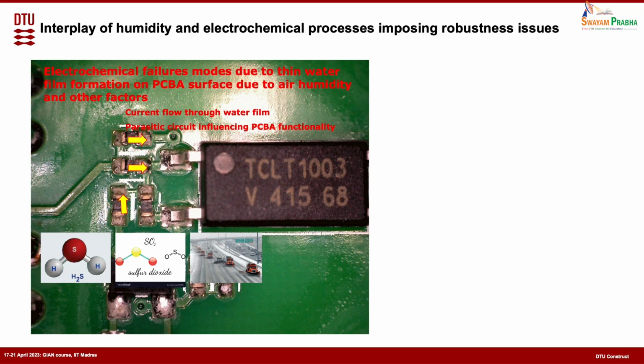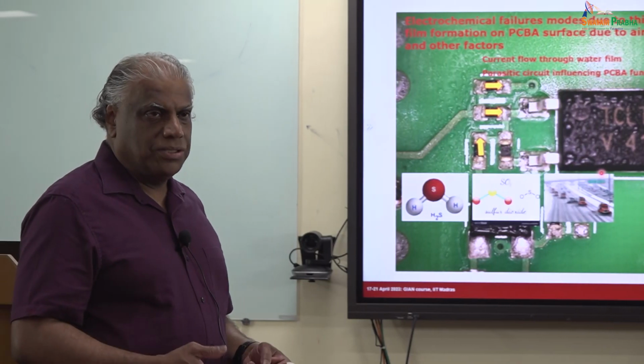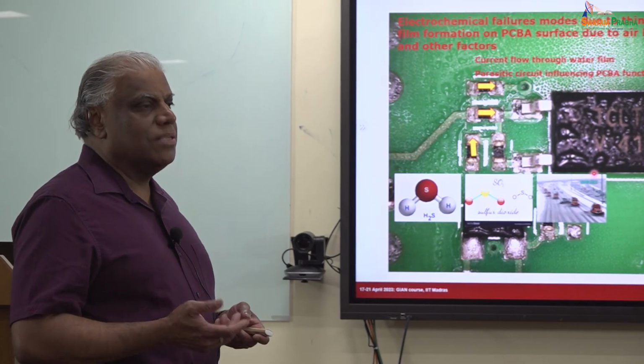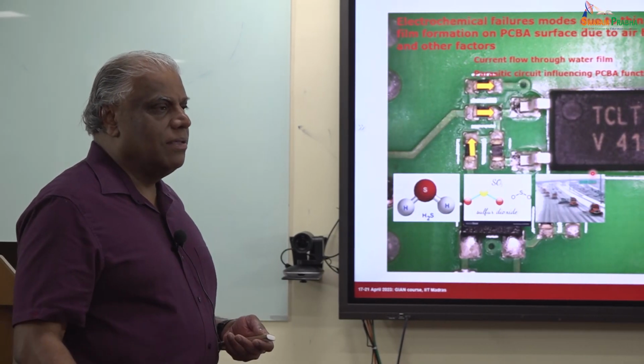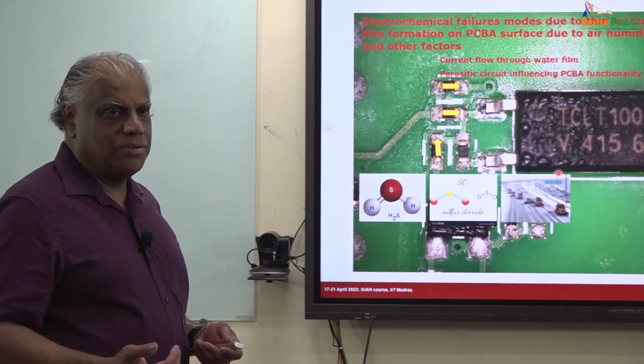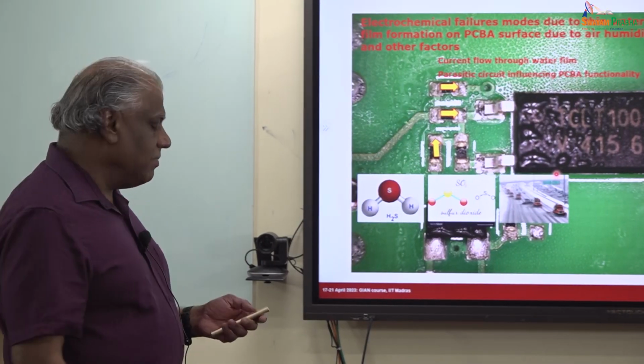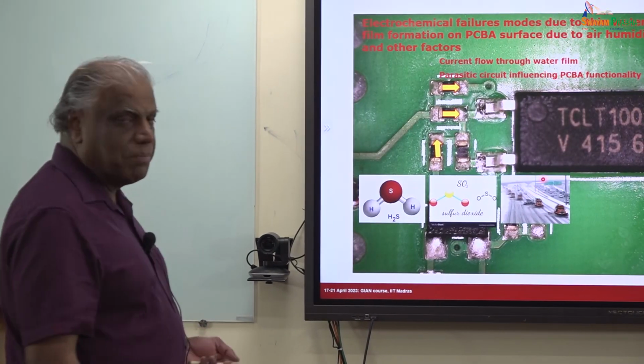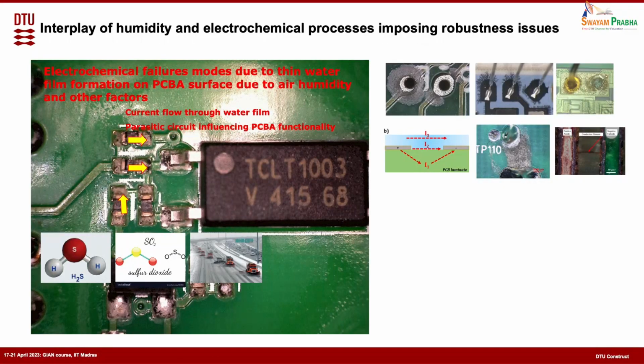Aerosols or things like that are less of a problem in electronics, because most of the electronics is packaged. When they package, they make sure that the packaging is tight enough so that only humidity and gases can go in, not the particles. That way the aerosols are not that big a problem for the electronics. And that will cause many failure modes. Although some failure modes are more important than others, in general it causes many failure modes. So this is a typical, we call it creep corrosion.